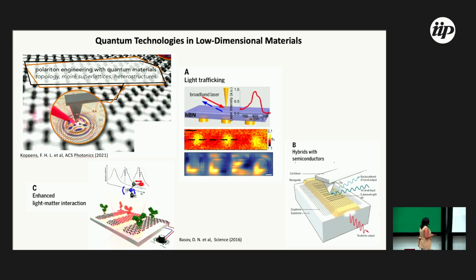So we use polaritons for several applications in optics. The simplest one is sensing. We can use plasmons as a sensor for several molecules. We can use, again, phonons or another type of polariton as a superlens, because the electromagnetic field is increased, and then we can see some structure behind the materials. It's a very common application. And nowadays, we can combine conventional semiconductors with 2D materials in order to make modulators, detectors, and so on.